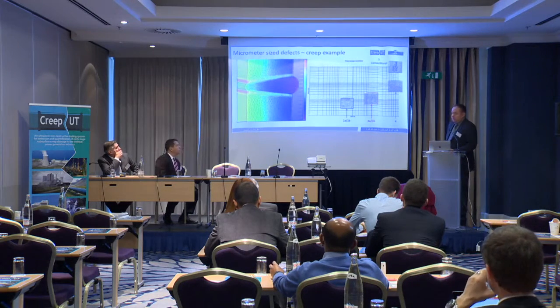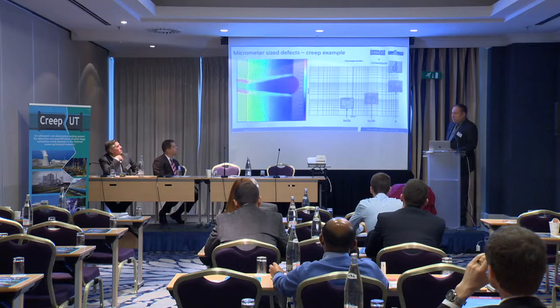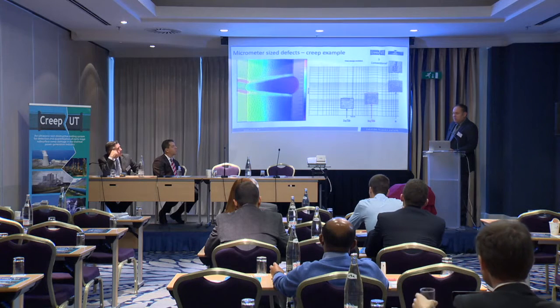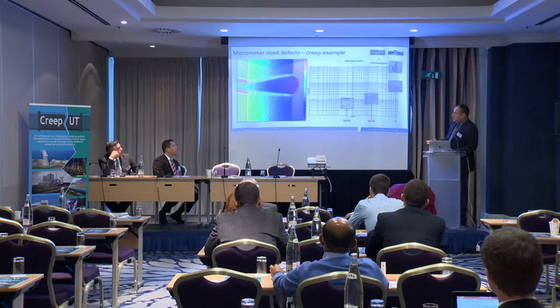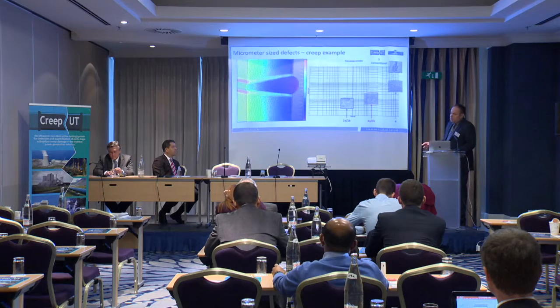So quickly about the creep again, we can make different theoretical models, we have experimental stuff. What is going on is that this damage is happening because of the different distribution of stress and temperature within the weld and around the weld, and it has several phases. First, very small defects, then these defects connect to larger defects, and then at the end the pipe can crack. And these different stages of the creep have different time scales. So the first phases are actually quite slow, and the last phase is really abrupt.